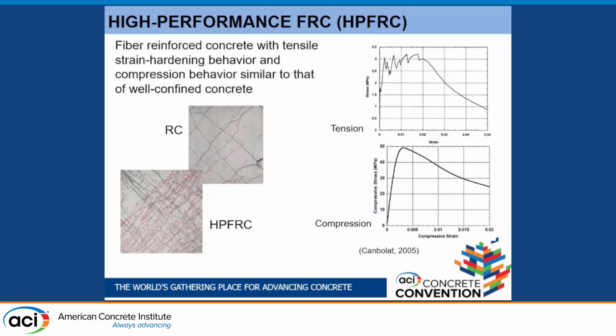Most fiber reinforced concretes exhibit a softening response after first cracking, so they don't have this hardening response. One advantage of this hardening response, besides the increase in tensile stress and strain capacity, is that it leads to multiple cracking.